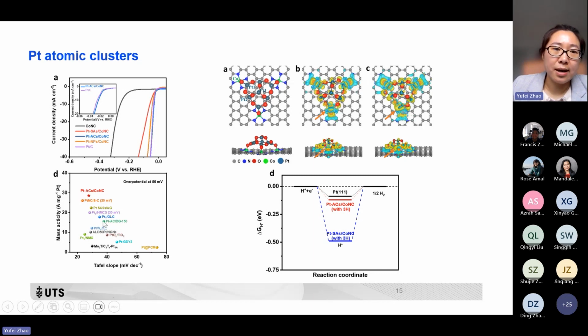When compared with the other published Pt-based catalysts, our catalysts still show much higher mass activity and also a lower Tafel slope. Then we constructed the atomic structure to try to explain why this material has shown really good performance and where the active site of this material is. As shown here, we have constructed platinum-oxygen-platinum atomic clusters, which are stabilized by the cobalt single atoms here. From this atomic structure, we can find two units that may be the active sites for the HER.